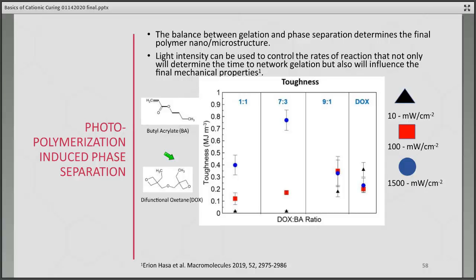Here's a great illustration that Erion Hasa has published to show this. It's the balance between the gelation and phase separation which determines the final polymer nano or microstructure, and the light intensity can be used to control the rates of reaction and determine your final properties. In this case, Erion Hasa took this acrylate hybrid system composed of BA, butyl acrylate, and this oxetane. If you just take the oxetane itself, he exposed the system to 10 milliwatts per square centimeter of light, 100 milliwatts, and 1500 milliwatts.